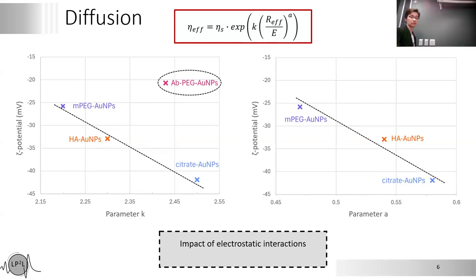Also with the specific coating, which is antibody at the end, because antibody is a way more complex molecule, we don't have only electrostatic interaction, and then it doesn't follow anymore. So it shows that even if this equation works pretty well, we still need to work on this equation to take into account all kinds of chemical interaction.